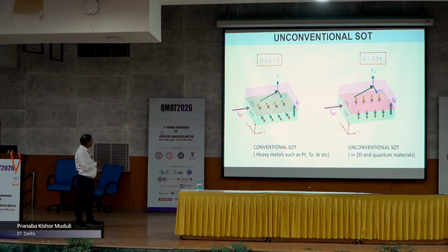If you look at a normal heavy metal like platinum, tantalum or tungsten, suppose you are passing the current along the x-axis, then you create the spin current which is flowing vertically, that is along the z-axis, and the spin polarization along the y-axis. So these three vectors are perpendicular, and this is known as conventional spin orbit torque.